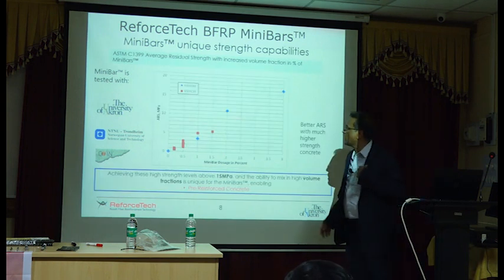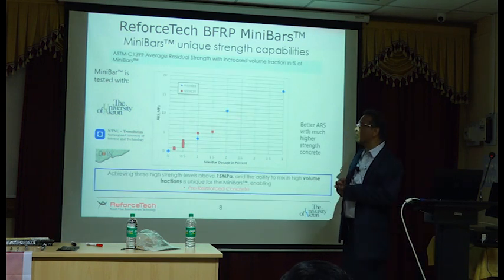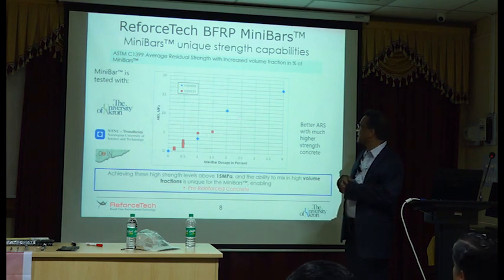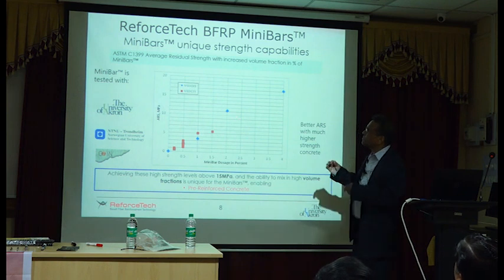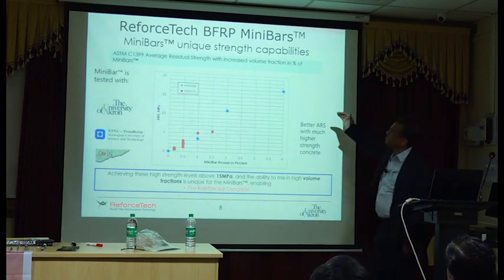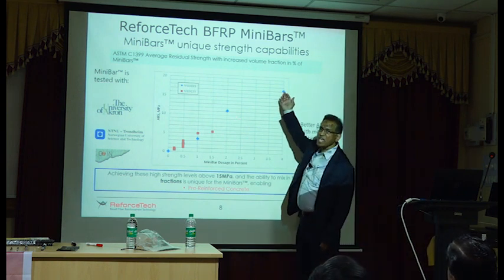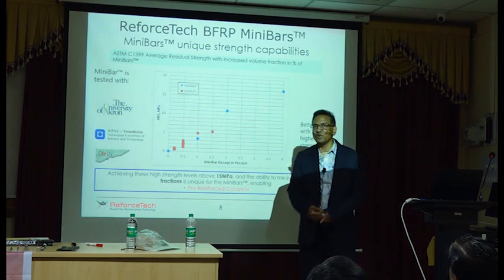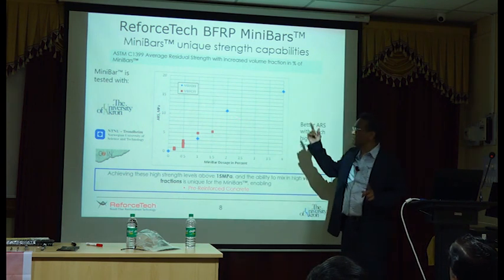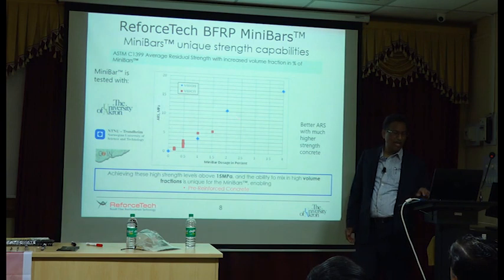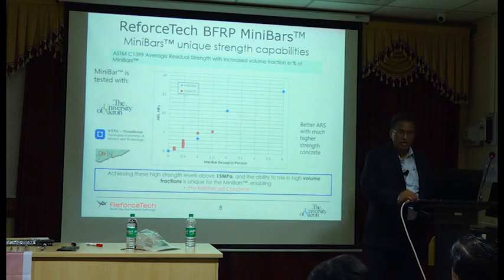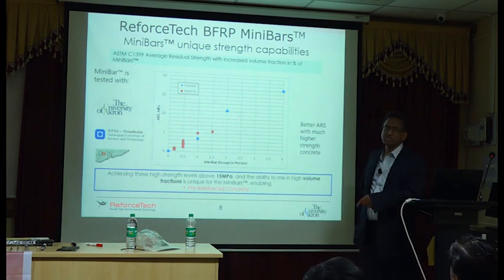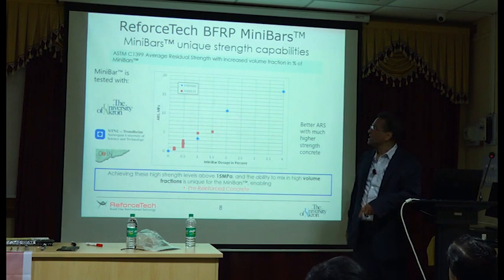So we were able to do the ARS test. You probably are familiar with the average residual strength test. And then we were able to get 15, even 17 MPa residual strength. I don't know if you have a feel for numbers, but that's a very, very high residual strength. Average residual strength is a standard test, ASTM C1399.